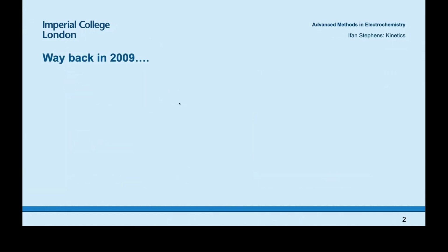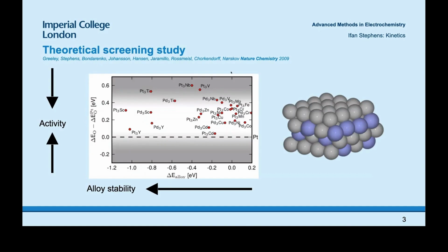and at the time, I was working with theorists, Jens Nørskov, Jan Rossmeisl, Heine Hansen, and Jeff Greeley, and they predicted using density functional theory calculations, so we were looking at oxygen reduction for fuel cells. We wanted to look at alloys to decrease the amount of platinum, so we wanted to look for more active catalysts for oxygen reduction. And they predicted, I won't go into detail about this, that platinum yttrium, platinum scandium, and palladium yttrium were very active catalysts for oxygen reduction from the theoretical calculations. They wanted me to do the experiments.